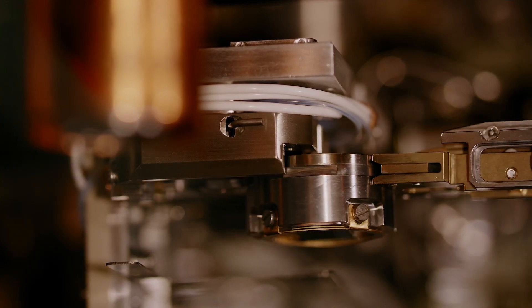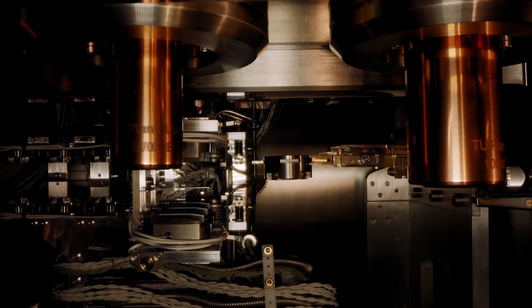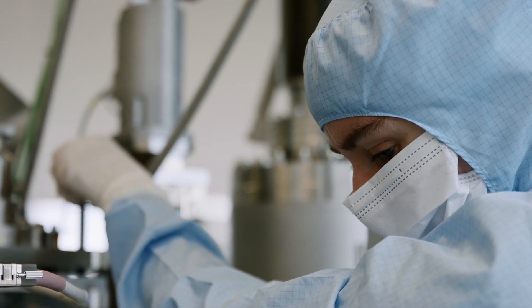The best thing about the UHV suite is that we can do all of our traditional fabrication steps within this ultra-high vacuum environment. We can take our substrates and load them through our load locks, where we can condition them all in parallel. We can heat them up to 900 degrees to anneal them and clean them in different gases, using different plasmas to ensure there's absolutely no contamination from the outside.